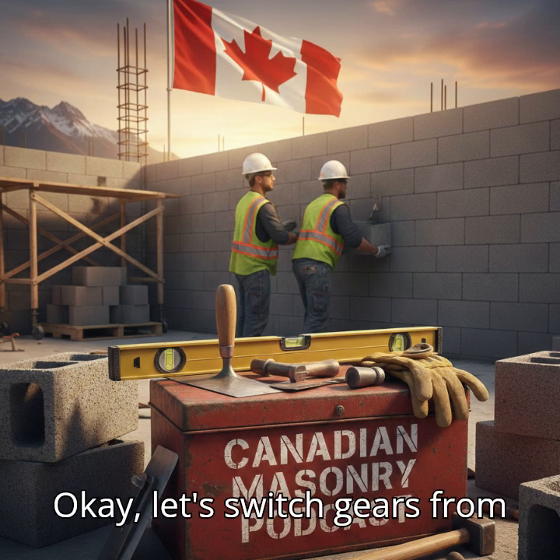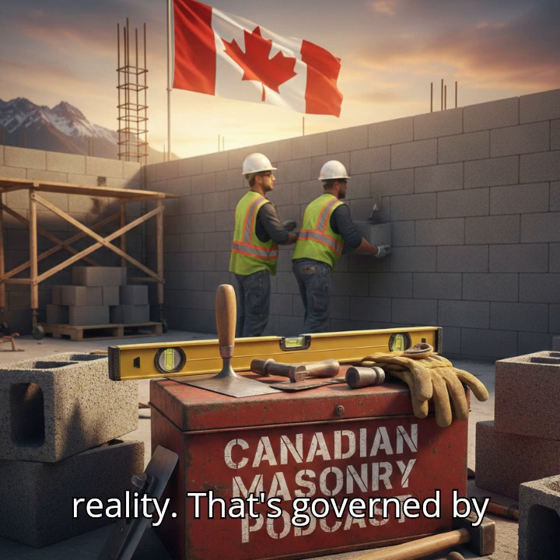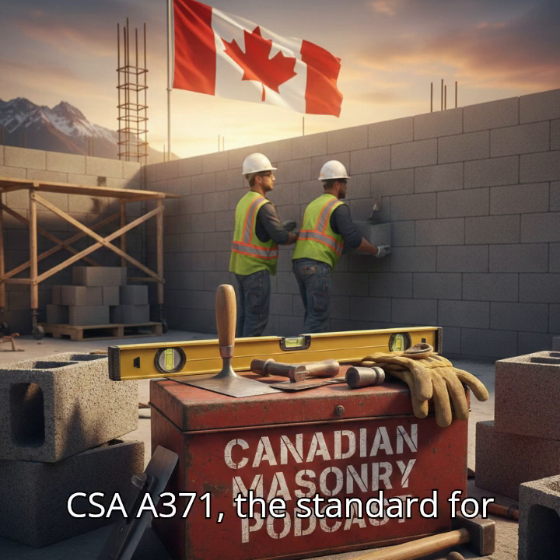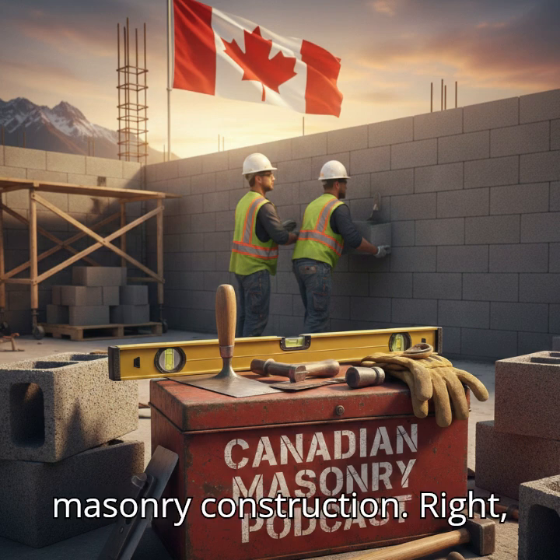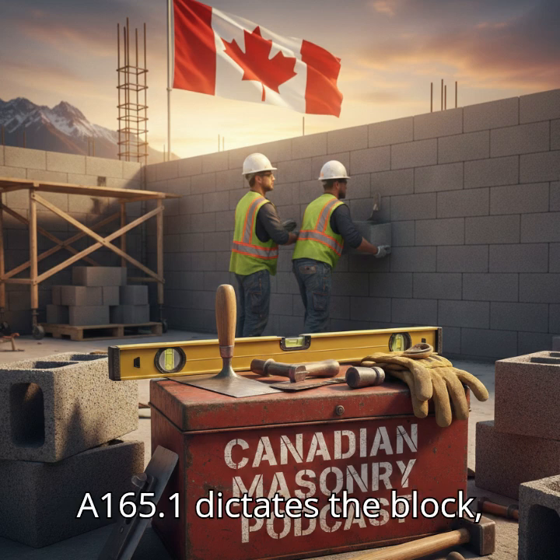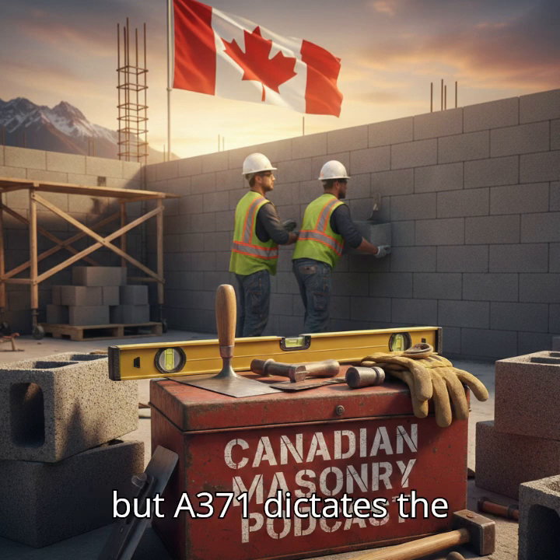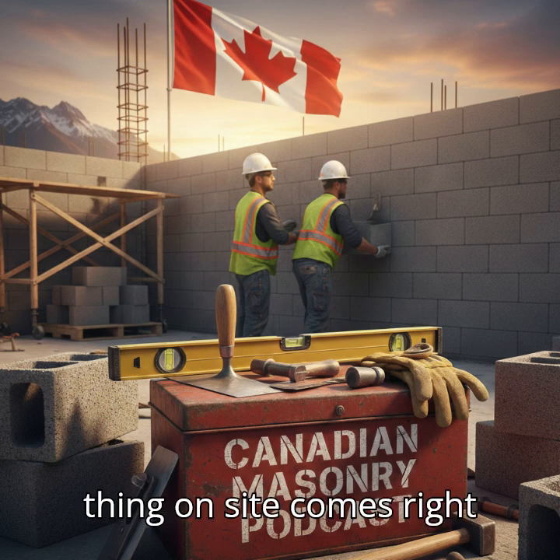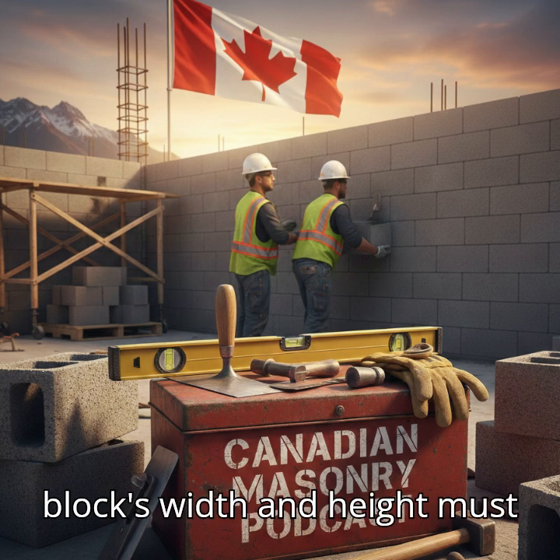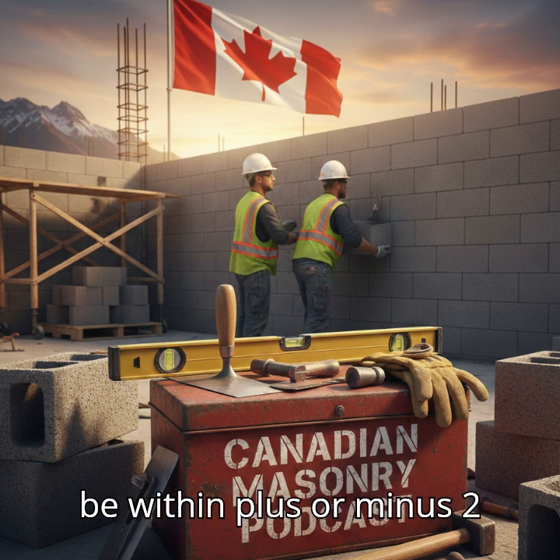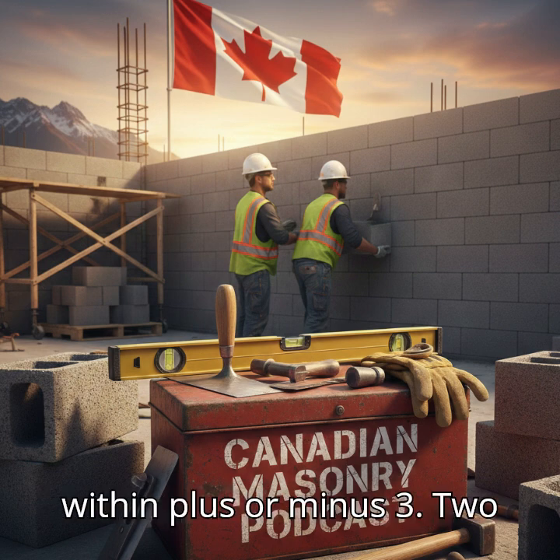Okay, let's switch gears from the factory spec to the site reality. That's governed by CSA A371, the standard for masonry construction. Right. A165.1 dictates the block, but A371 dictates the installation. And the first thing on site comes right back to the manufacturer's promise, dimensional tolerance. It does. The block's width and height must be within plus or minus 2 millimeters. The length's within plus or minus 3.